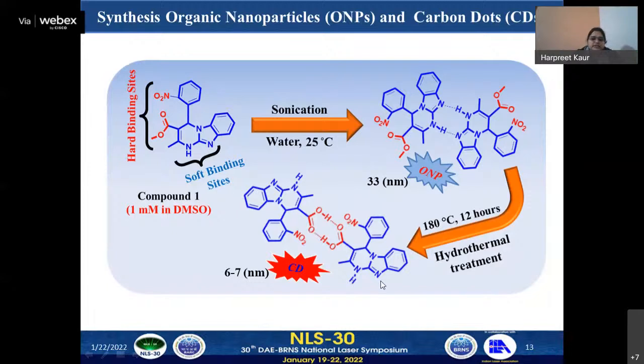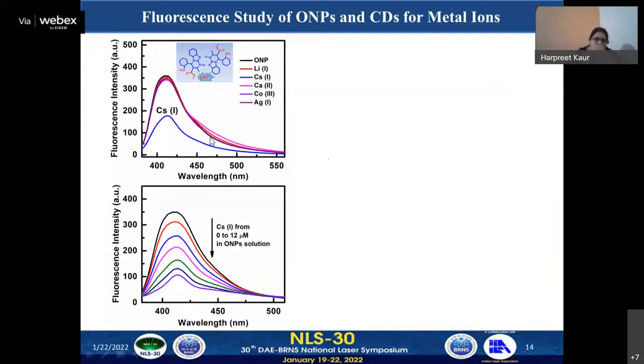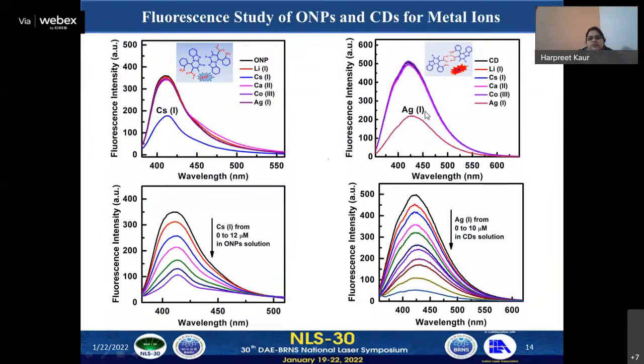And the fluorescence studies have shown that these organic nanoparticles selectively bind with the cesium ion, whereas the carbon dots selectively bind with the silver ion in the aqueous medium. And from the interfacial study, we have observed the SFG spectrum for organic nanoparticles, in which we have found there is no change in the SFG spectrum as compared to the interfacial pristine water structure.